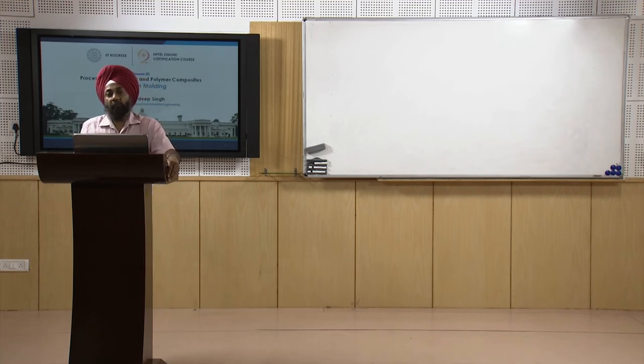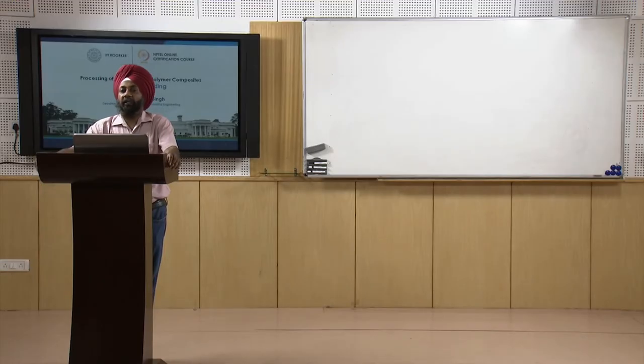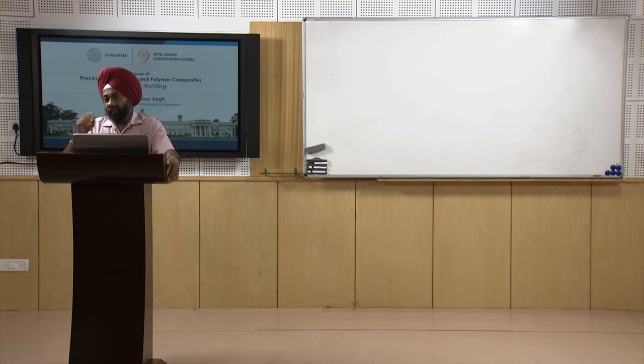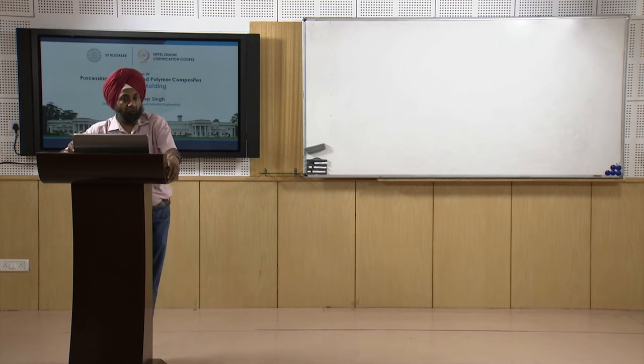A second problem with hopper-fed fibers is that the screw's rotation can shear the fibers, reducing their length and causing damage so they cannot fulfill their reinforcement purpose. Studies have confirmed degradation of fiber properties when fibers travel through the full barrel length alongside the polymer. Therefore an advanced approach is to introduce fibers just before the polymer enters the mold cavity.